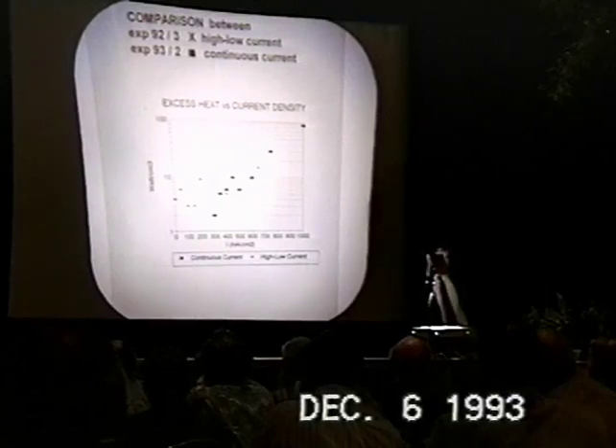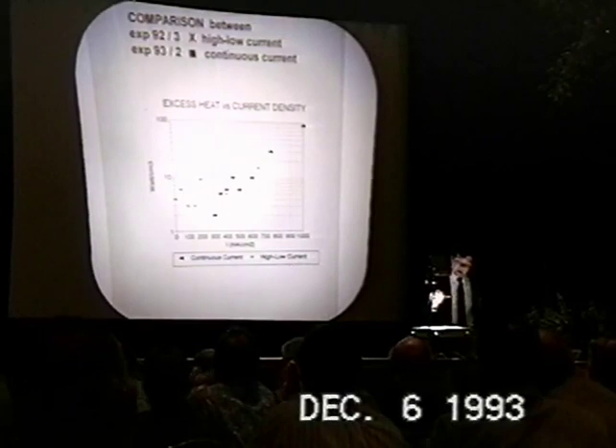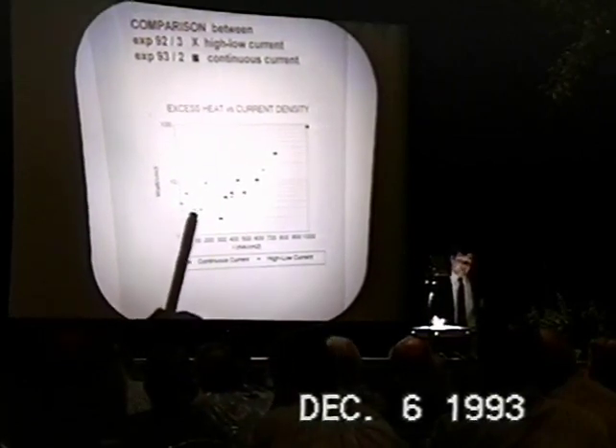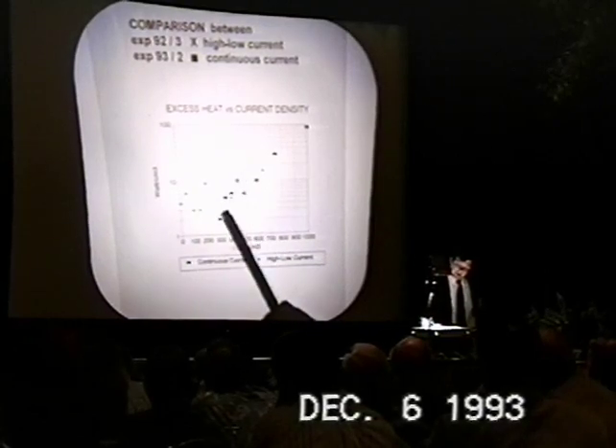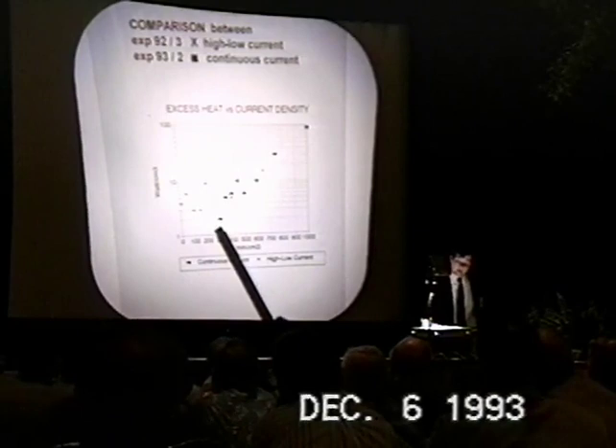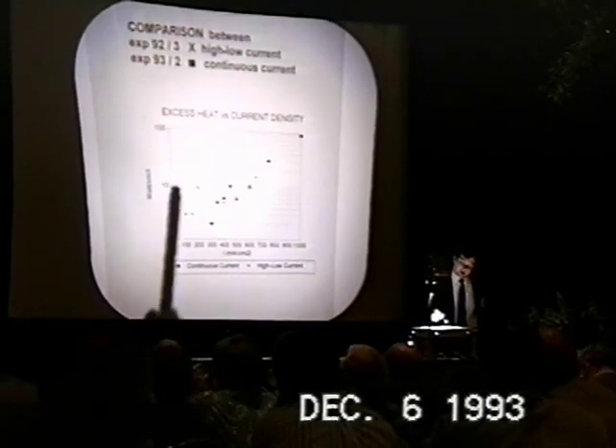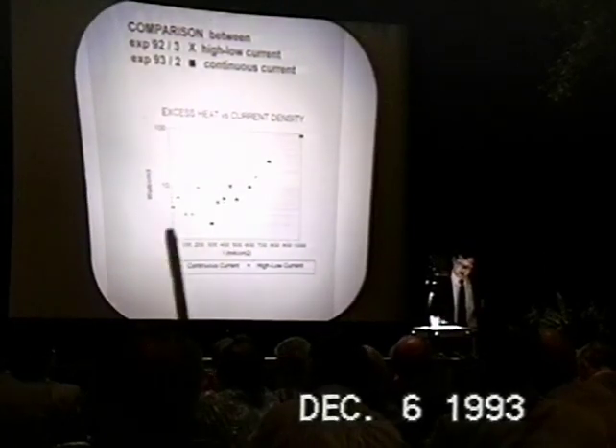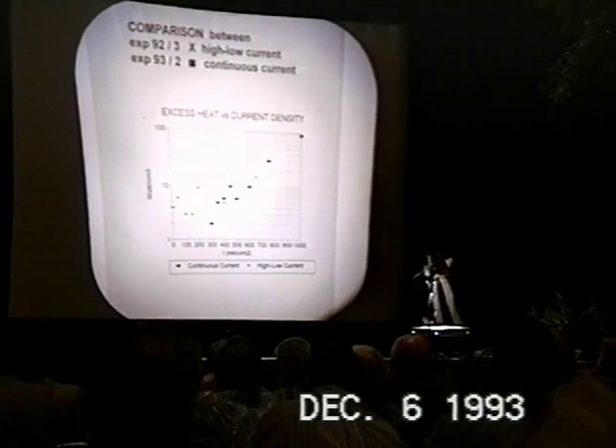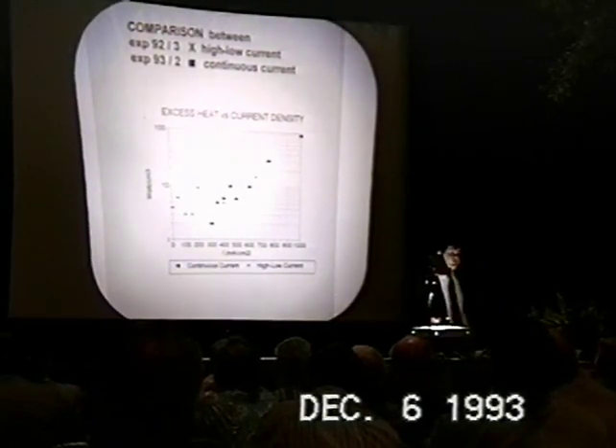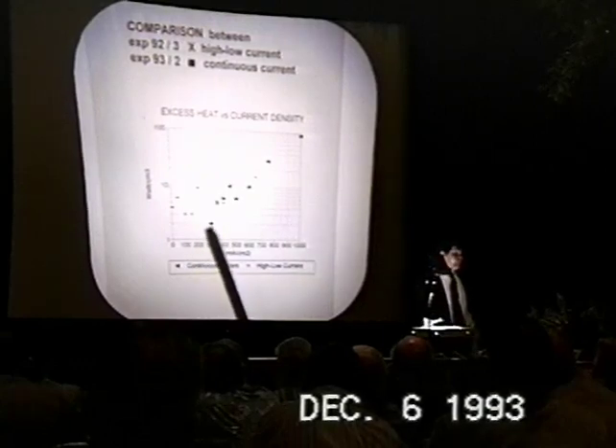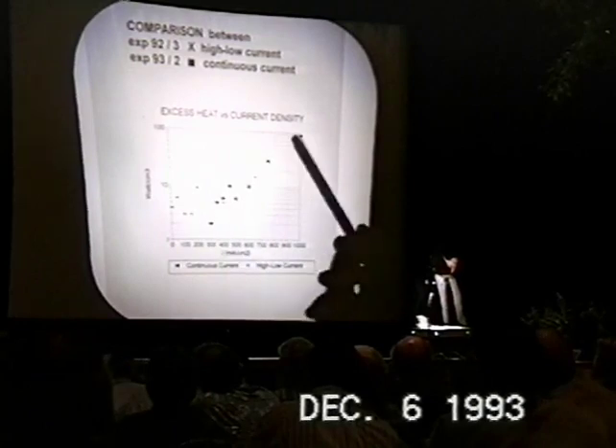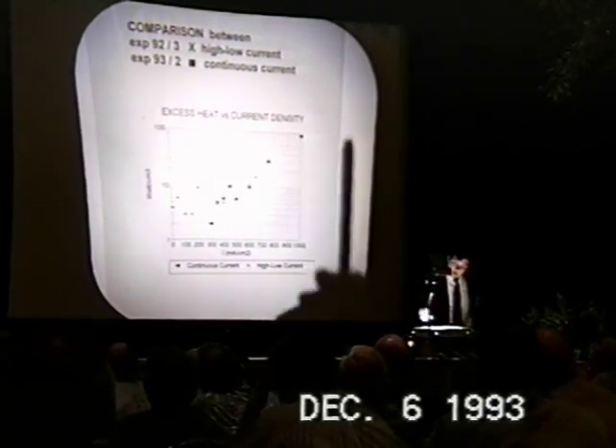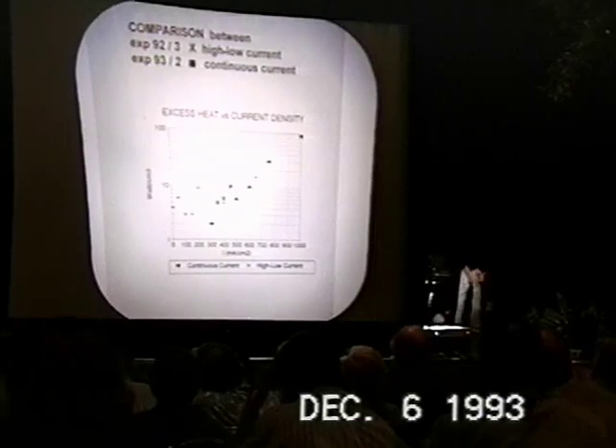It could be related to material problems, because this batch, the 92 palladium, is an old batch, and the 93 palladium platinum is a new one. So it could be correlated with this different batch, or maybe it could be the high-low current technique. But we think that after a certain current density, after 200, 300 milliamps per square centimeter, the bulk is working very well. We also achieved around 100 watt per cc. And that's it.